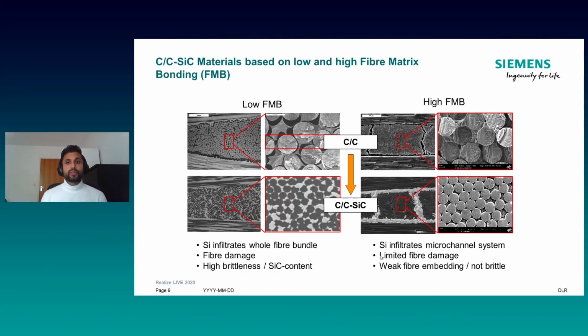And in the case of high fiber matrix bonding, we'll end up with the desired microstructure where only the carbon matrix or the fiber on the edge of these CC blocks react with silicon to form silicon carbide, and the CC bundle itself remains intact and it provides this damage tolerant behavior to our material.